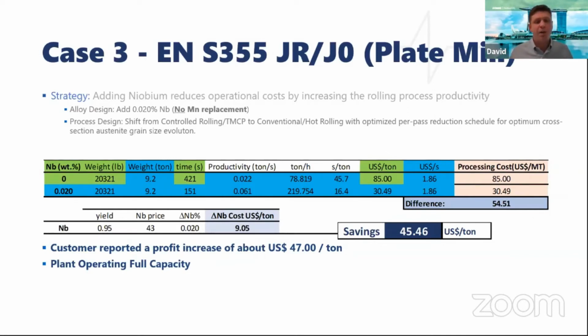And in this case, a 200 ppm addition of niobium could manage to produce it completely conventional rolling. No control, no delay, full speed to basically the limit of the reheating furnace, which was about 220 tons per hour, bringing an extremely expressive savings of $45 per ton. And the customer reported a profit increase of about $47 per ton. This is an extreme case, I know, but I like to show it because it's a real case. And many plants that do not operate, roll the whole year long, or that are operating full capacity right now, can benefit in a very expressive way from NPO.